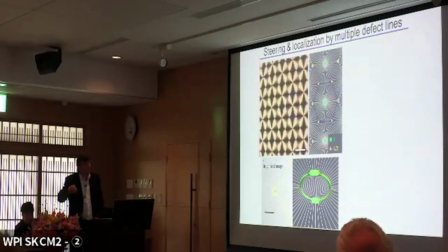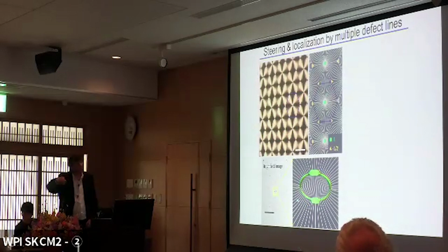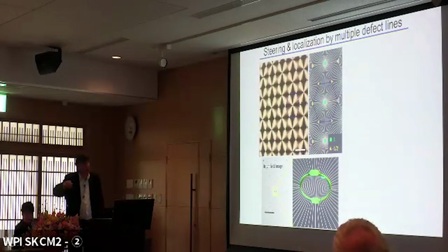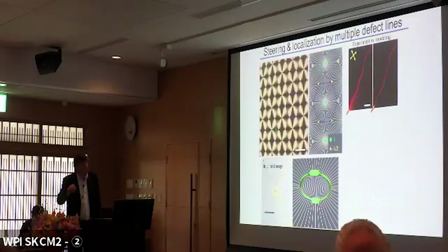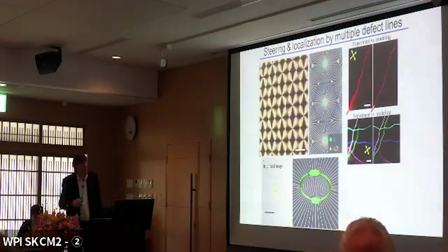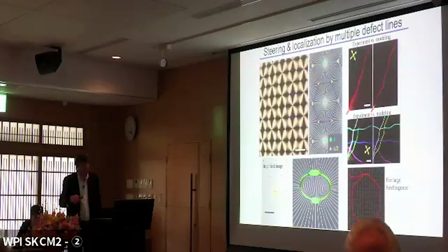And here you see these vortices that run perpendicular to the screen, and integer strength vortices, interestingly, tend to split into half integer ones to minimize the elastic energy associated with them. So for every integer winding number vortex, we'll have 2 vortices in the bulk of the liquid crystal. Now, as we send a laser beam of light, we can see it meandering in here between the vortices in this array. And the experimental traces are very closely consistent with computer simulated ones for different beams that you can see in here in different geometries.